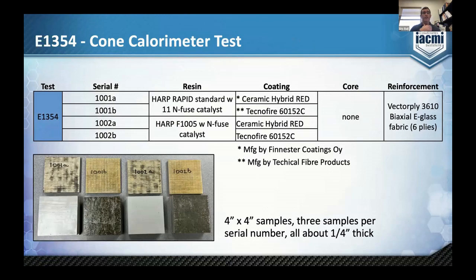So we put together 4 different tests for the calorimeter test. We had 2 different resins along with 2 different coatings, and we used a ceramic hybrid coating manufactured by a company in Finland called Finnester Coatings, as well as a Tecnofire product manufactured by Technical Fiber Products. All of these samples here were non-core. These are just solid laminates to help us determine what was going to do best looking at the E119 test. And so these are the coupons here in the picture, 4x4 samples that were run in that calorimeter test.